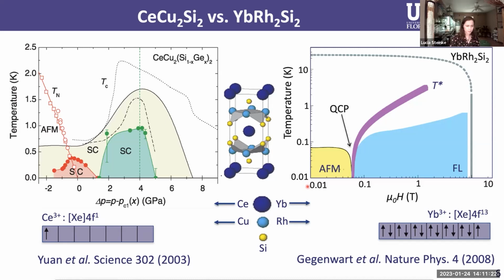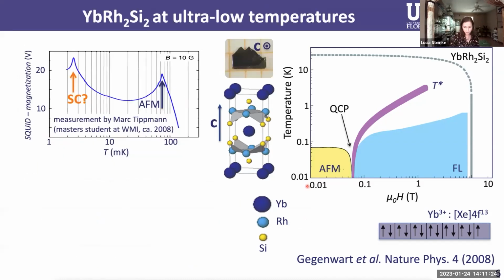For that, they collaborated with the Walther-Meissner Institute, where they had a microkelvin facility somewhat similar to ours, and at first measured the magnetic properties now to much lower temperatures. They could verify in the DC magnetization versus temperature that there was the antiferromagnetic phase transition at 70 millikelvin. But then as they cooled the samples further, they saw a second very pronounced peak that indicates that there is another transition happening. And we were speculating that this might be a superconductor.